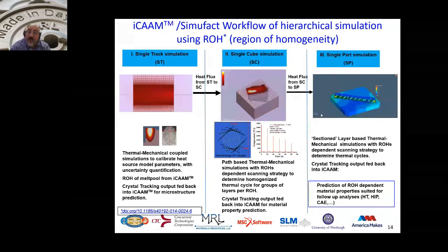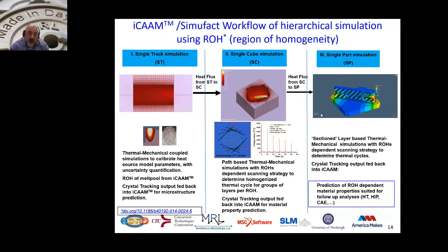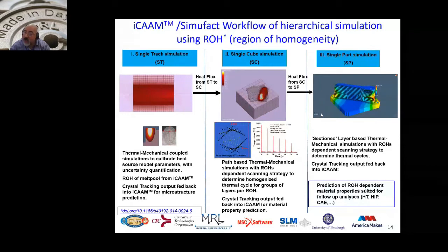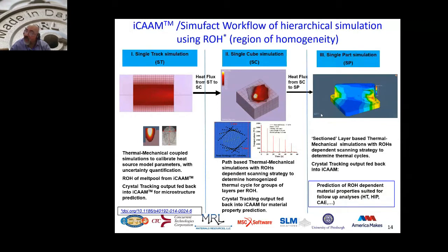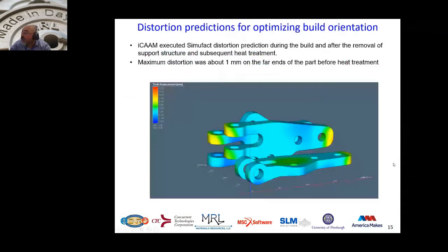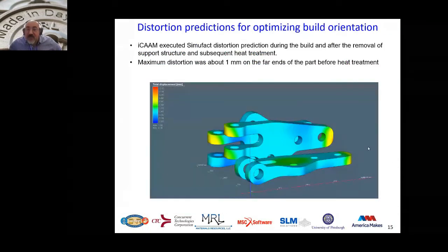And you are seeing the single part now being built layer-wise, and the information is fed at the layer level or at the region of homogeneity level, which allows us to capture the thermal profile in various locations and the most critical location, which helps us to predict later on the microstructure as well as the post-processing that we will need to do later on. And the information was used with SimuFact to predict the residual stresses, and this is some of the orientations that were selected.